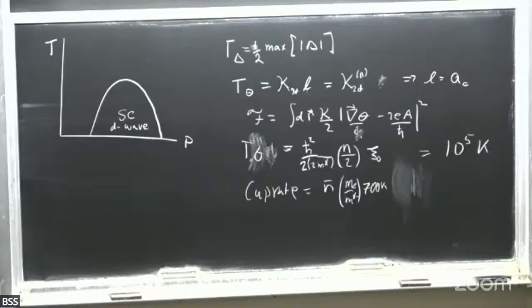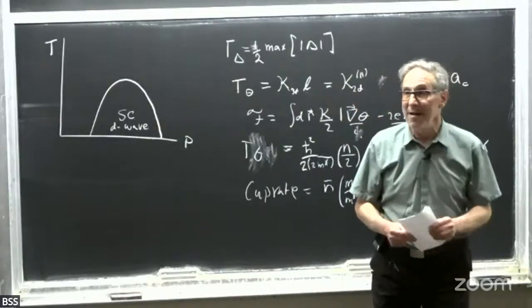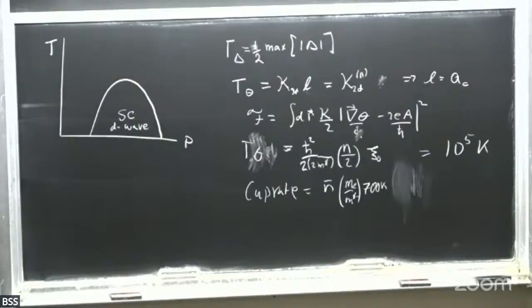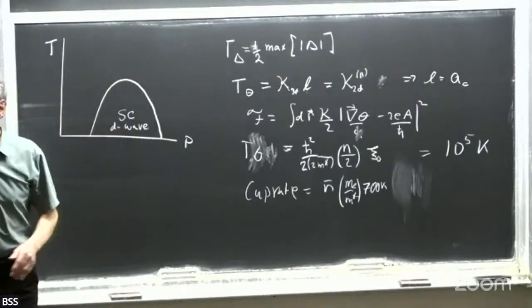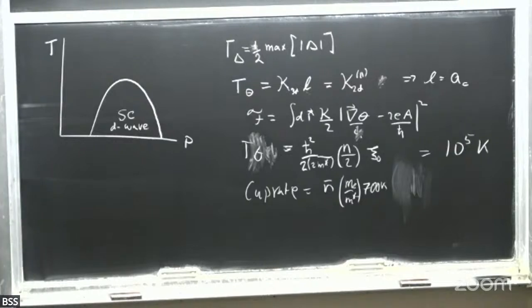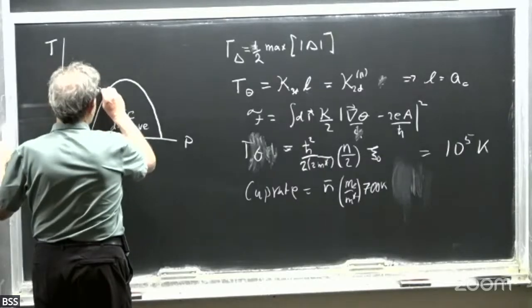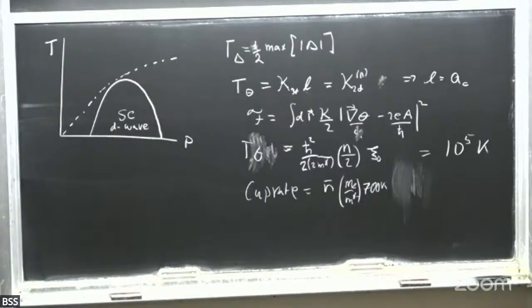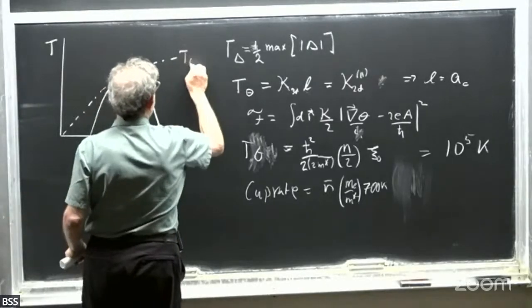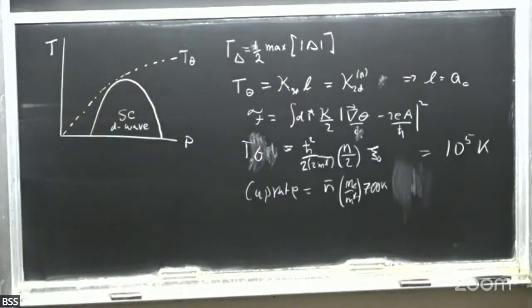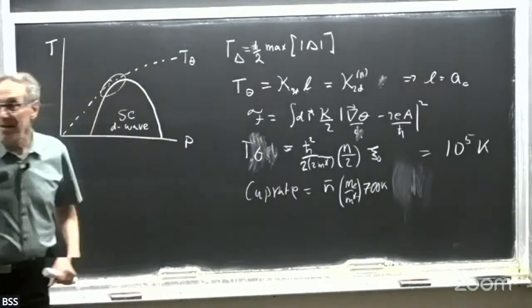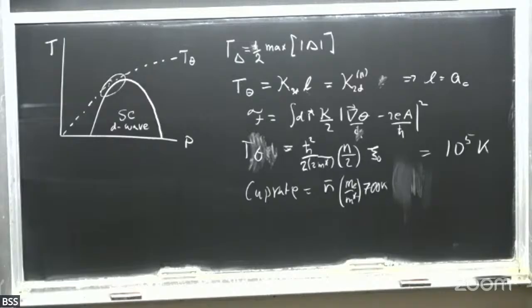So, well, okay, you can also measure this quantity. And if you measure this quantity for optimally doped cuprates, you get a number that's very close to being equal to Tc. So Vic and I abstracted from this, and we drew a sketch like this. We said, look, probably the superfluid density has got to vanish as you approach the insulating phase. So we said, probably we should be drawing a form like this for T theta. And there was data here on the underdoped side that showed that both Tc was equal to T theta and that Tc varied in the same way.